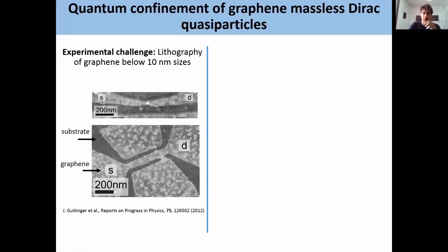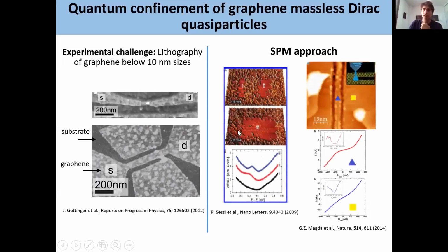It's been there since the beginning of graphene, and usually to do this, what you use is standard lithography. But the problem here is that with standard lithography, you cannot go below 10 nanometer sizes. Even now, you cannot go below this. It's very complicated. So of course, STM has something to say in this lithography methodology, and since the very beginning there have been attempts to do lithography on graphene using the STM tip.